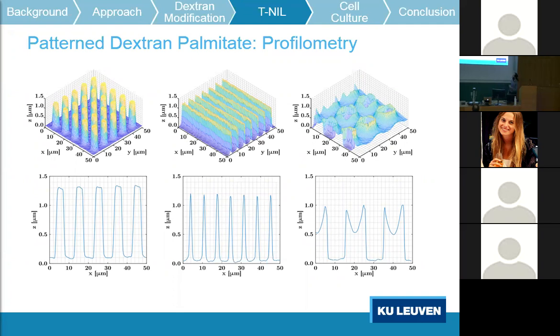But in seeing this deficiency in the procedure itself, I saw something else rather interesting, and that was a difference in roughness between the areas where the material flows, such as in these pillars, to the spacings between them. So what I mean by that is the tops of these pillars here had a significantly increased roughness compared to the bottom of the pillars, and the same with the gratings, and of course, the same with the pits here. And I thought perhaps this could have a large impact on the properties of this material itself. And so I investigated to see how this roughness would